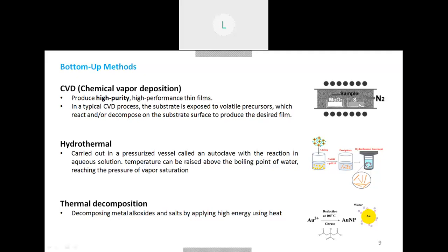So you can also go for the double split, like sulfur has a lower boiling point, so if you keep it in a separate zone where the temperature can be controlled, you could find different types of materials or films over the substrate. But the problem with it, you will find a very small yield in CVD. The hydrothermal is the best method in my view, because you can get the yield high. A small instrument is there, which is called the Teflon lined autoclave, jacketed by steel, and you keep all your reactants in it, and you keep that reaction sample in the oven for a time, and you get very purified and highly crystalline nanostructures.